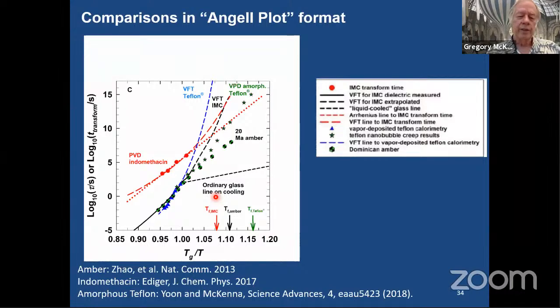And this just shows an Angell plot of the same data, and it compares it with some work that Mark Ediger did. He had 4 data points on physical vapor deposited indomethacin, where he was looking at it devitrify, and he decided to fit this line through it, and that's what he thought was happening. This was his Arrhenius line, which fits just as well through the 4 data points he has, and he didn't actually go below Tg. So what we see is the Vogel-Fulcher behavior is just not followed for either the amber or for the vapor deposited Teflon.